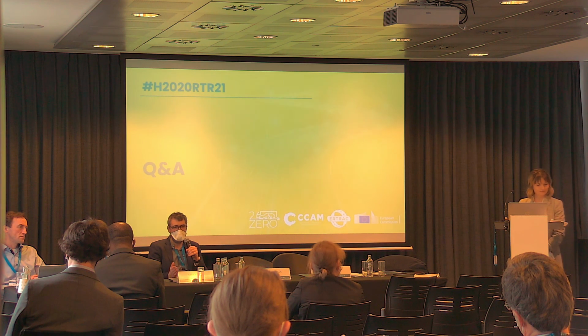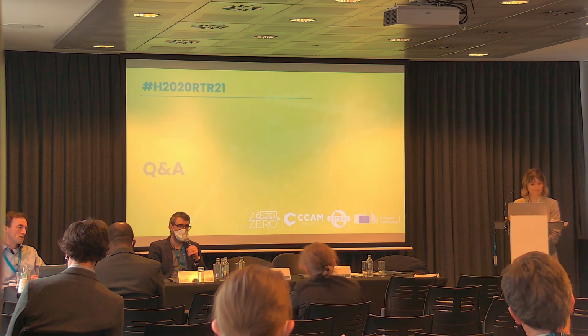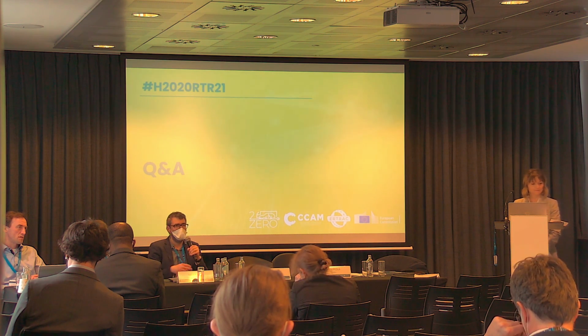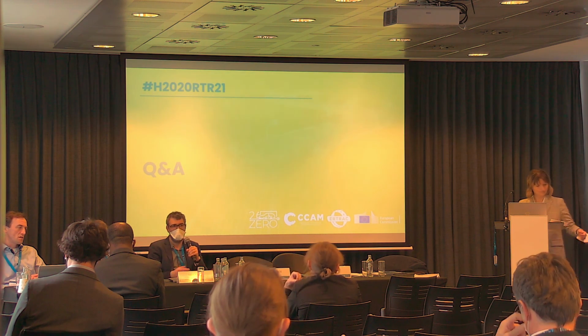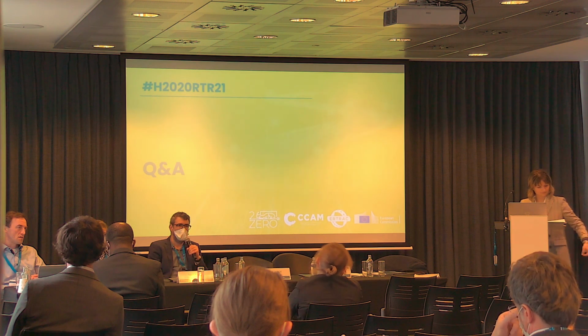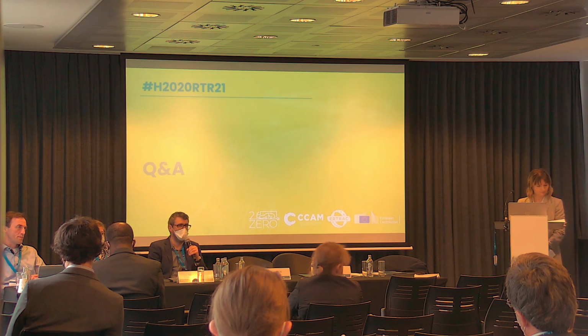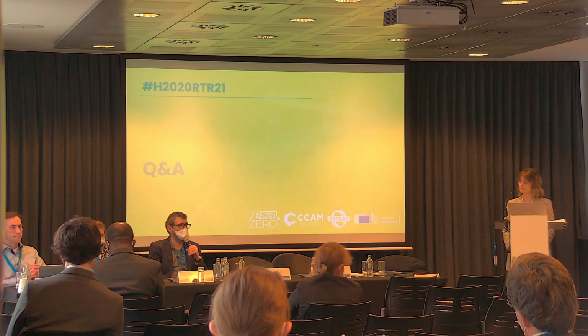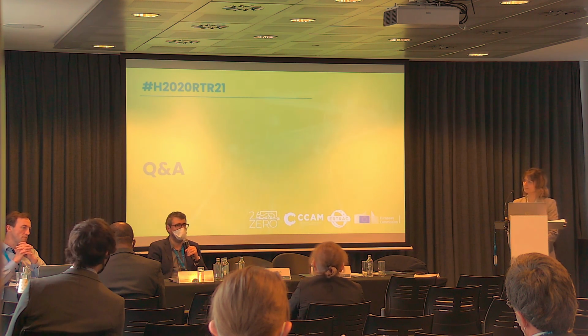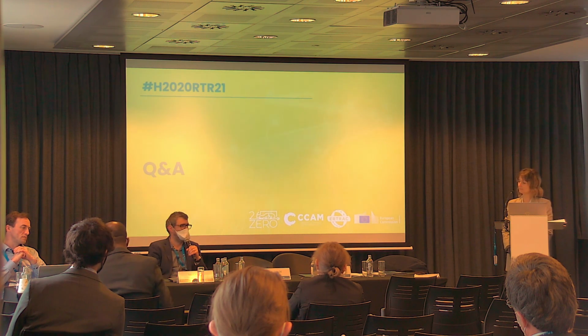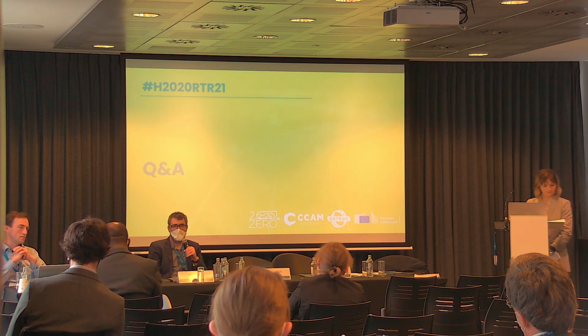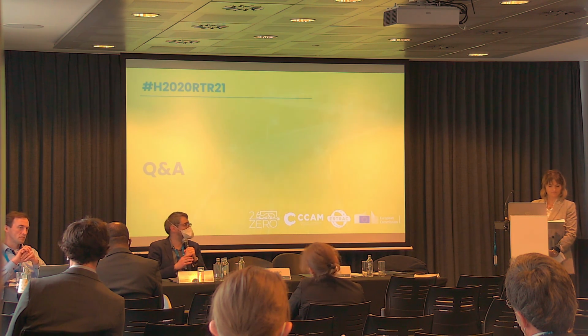We need also to focus on the right time scale and right length scale for what we want to do. For instance, if we want to go for aging, for 20 years aging simulations, it's very complicated to go with fully resolved 3D modeling, but doing some 1D modeling with specific assumptions is fast enough, and we have sufficiently good results. So with a good choice of assumptions, it gives us sufficiently good results to predict the behavior of the cells.